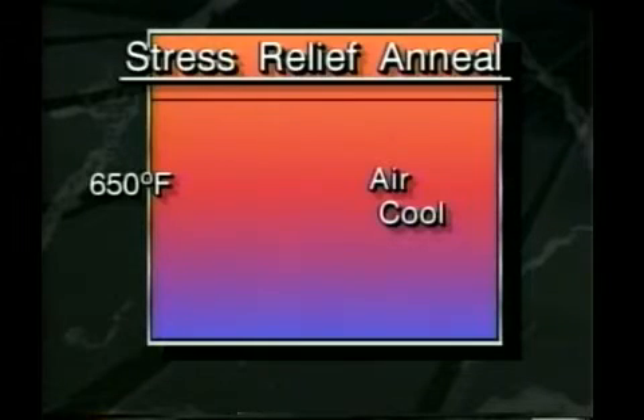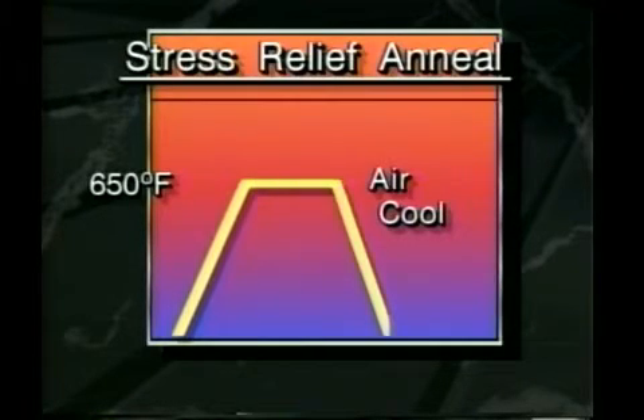A stress relief anneal is usually performed by heating the material to 650 degrees and holding for 1.5 to 2 hours, and then air cooling. The 650-degree temperature is high enough to stress relieve the cold-worked grains, so they transform into stress-free grains. This temperature is not high enough to dissolve significant amounts of hardening solutes into solution, so the air cool is adequate to achieve a significant softening and stress-relieving effect.